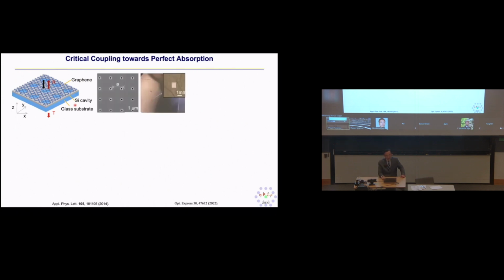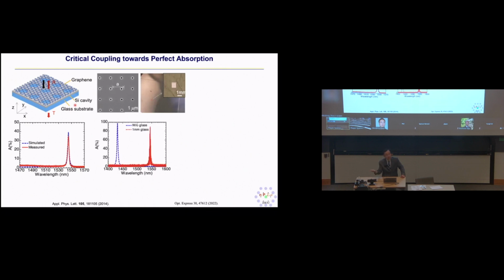But if you design right, you can get about 50%, the symmetry principle, right? At the most, they can get 50% in this case. If you add a mirror on the bottom to break the symmetry on a vertical dimension, you get 100%. So now you can have a very simple structure to get 100% absorption from a very thin layer structure. That could also be interesting, especially if you care about a spectral selective lattice structure here.